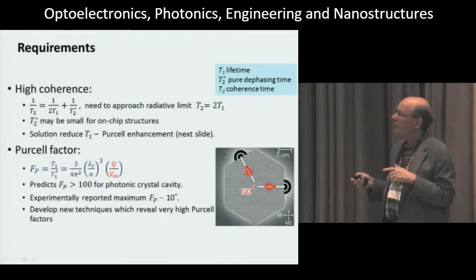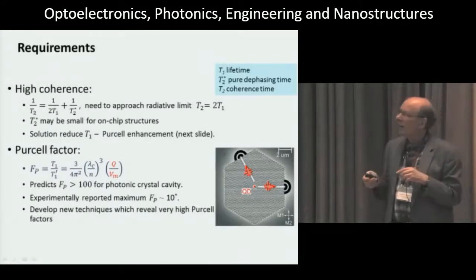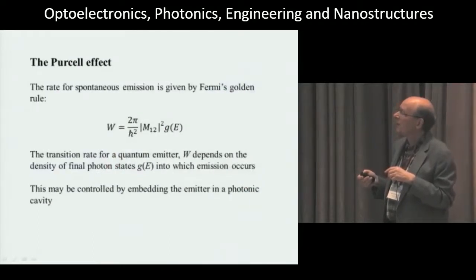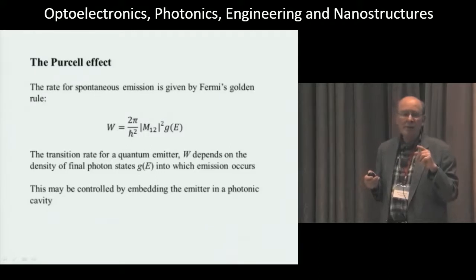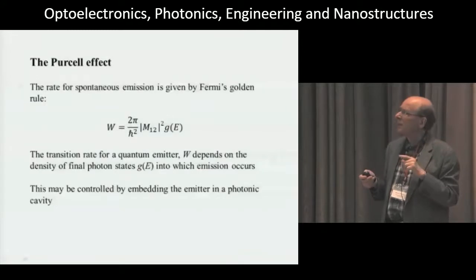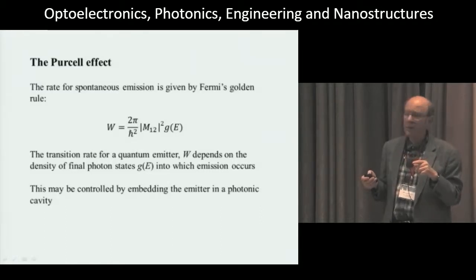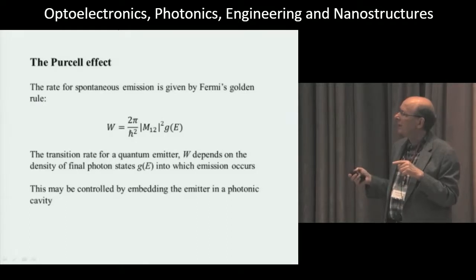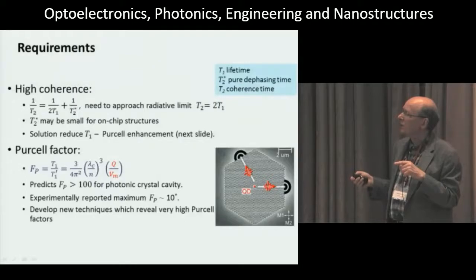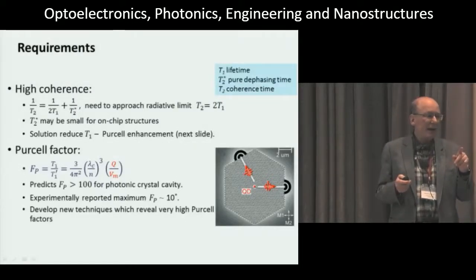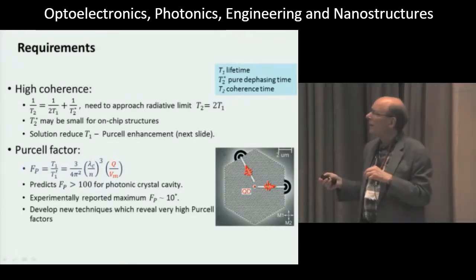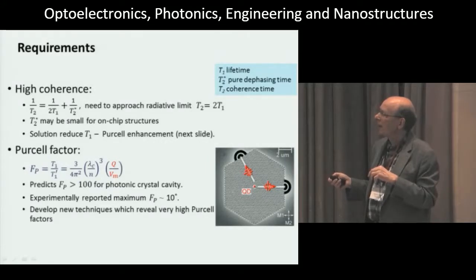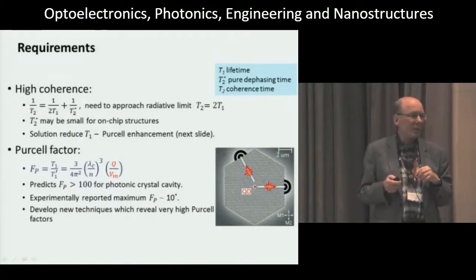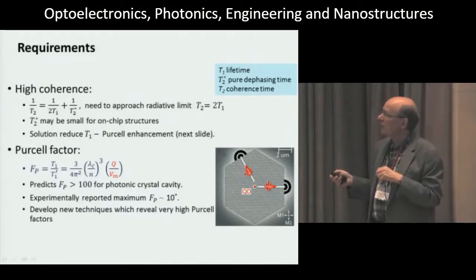The Purcell effect is that the rate of spontaneous emission depends on the density of final photon states. So if we can increase the density of final photon states, we can enhance the rate of radiative recombination. And we can do this by embedding the emitter in a photonic cavity. So the Purcell factor, which is the ratio of the lifetime outside a cavity to inside a cavity, is given by the Q factor of the cavity divided by the volume. And simple substitution for a very small cavity predicts Purcell factors of about 100. Up to our work, the maximum reported Purcell factors were about 10.